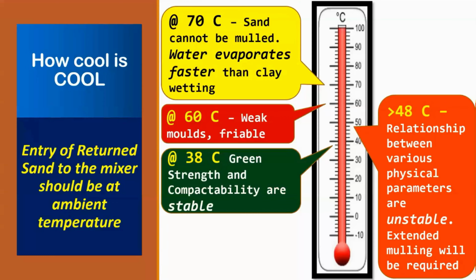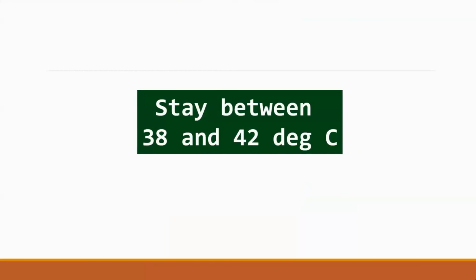And you won't be able to make the mold because by the time the hot sand reaches the molding machine, it has lost its compacting ability. So by compressing it, it's not going to make a good mold. When you remove the pattern from the mold, sand is going to collapse or it is going to get rubbed out. So better to stay between 38 and 42. So this essentially tells why cooling of the sand is very important in the process of reconditioning.